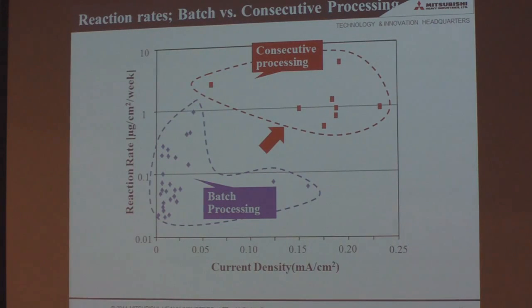This is the summary of reaction rates of batch versus consecutive processing. This axis is current density, and this is the reaction rate, in micrograms per square centimeter per week. This is the result of batch processing using electrochemical permeation here, and consecutive processing, the new experiment, is here. And you can see that the new type of experiment obtains a higher reaction rate compared to batch processing.